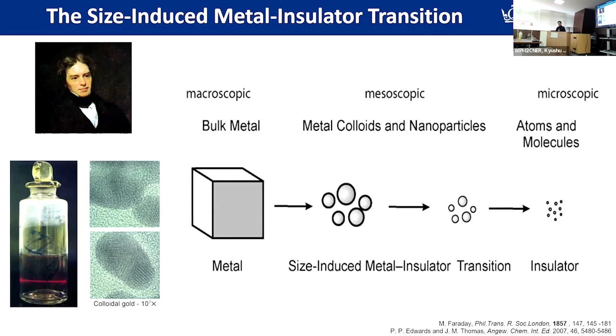What it tells us is that a bulk metal appears to be a good conductor, and it can conduct electrons very well. But scientists found that when we divide this bulk metal into smaller particles, from several microns to the nanoscale, even to the atom scale, all of a sudden the metal becomes an insulator. And in that case, it now interacts well with the microwave. So then we could use this metal under the microwave with control of the size.